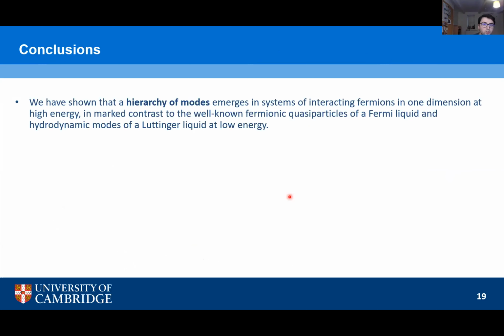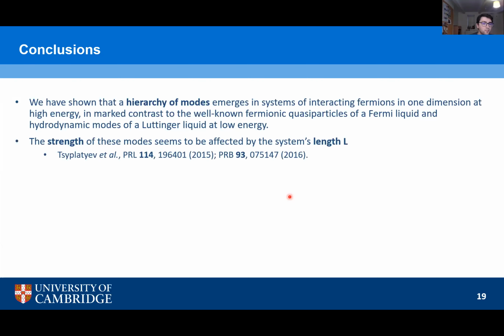So just to conclude, we've shown a hierarchy of modes emerges in a system of interacting fermions in 1 dimension at high energies. This is in clear contrast to what is predicted both by Fermi liquid and also by the linear Luttinger liquid model. This is consistent with the model proposed by Tsyplyatyev, the hierarchy of modes picture, where these modes should emerge as a function of system length.